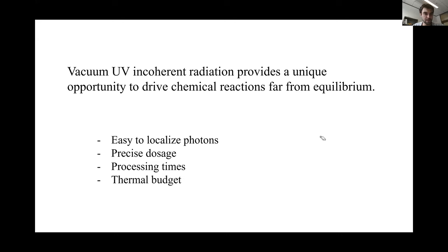The processing times, I will give you a couple of examples in the end, are extremely fast because in our case, we don't need to use vacuum. We just use nitrogen at atmospheric pressure to do all the processes. In thermal budget, so I'll just give you a hint. We are able to deposit materials such as SiO2 at room temperatures, which is obviously a huge advantage. And I believe this is the first technique that allows deposition of SiO2 at room temperatures.